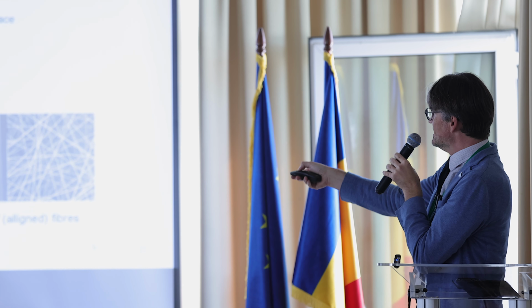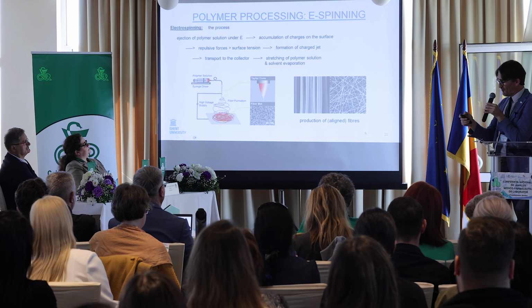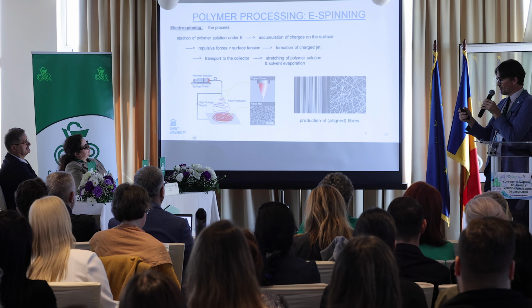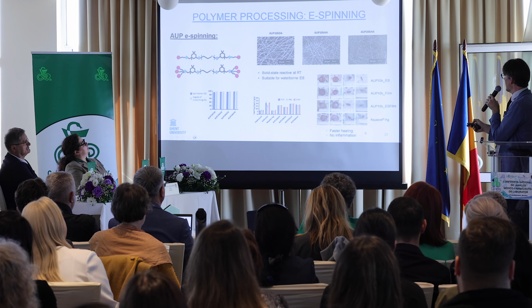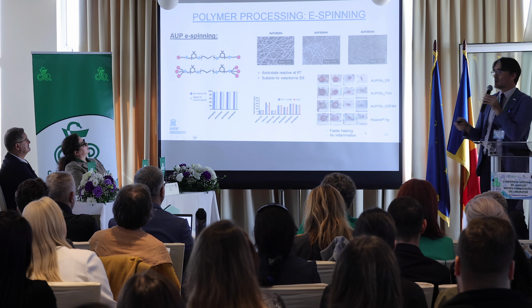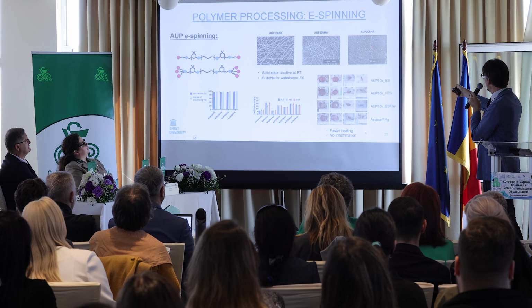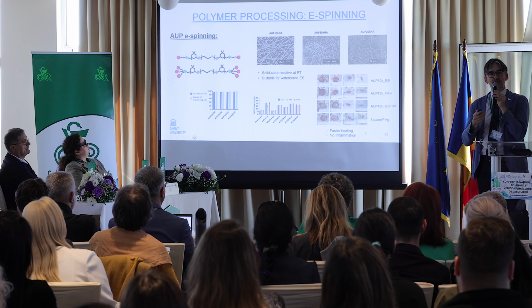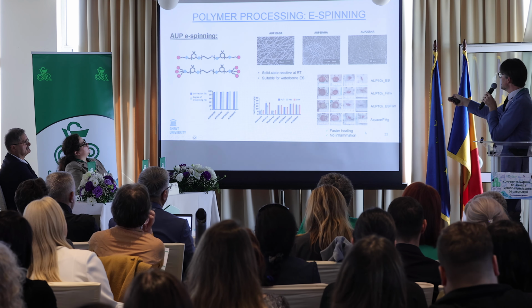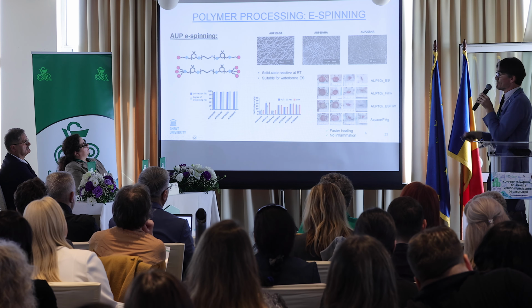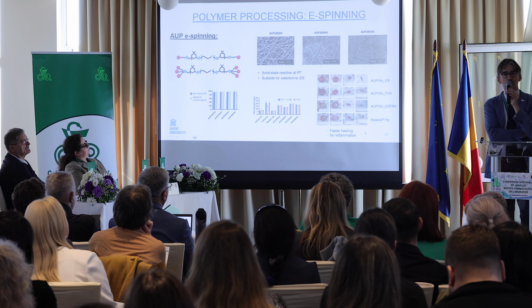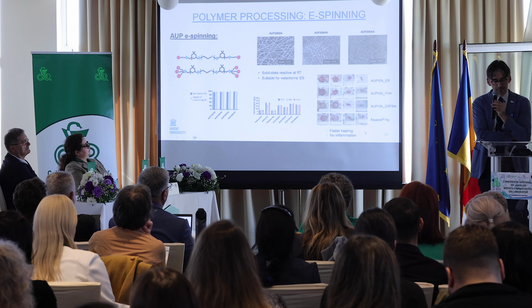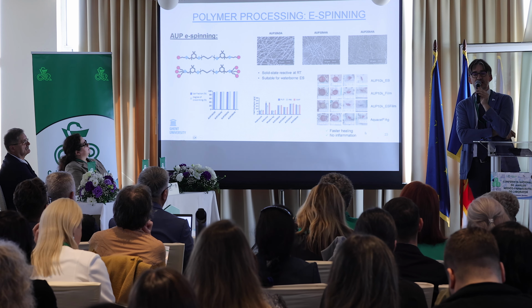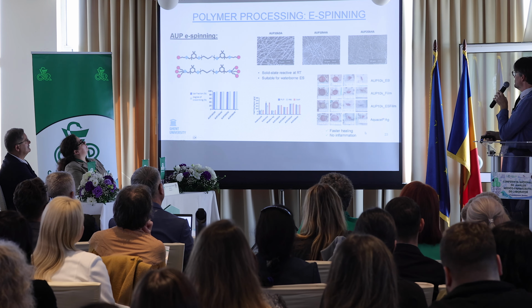So with this technique, electrospinning, both fiber geometries, morphologies can be easily obtained. Using our polymers, we have been evaluating whether or not they could be electrospun to produce those polymer fibers. And with each of the developed building blocks, after a long time of optimization, we could actually produce these electrospun mats in a reproducible fashion.